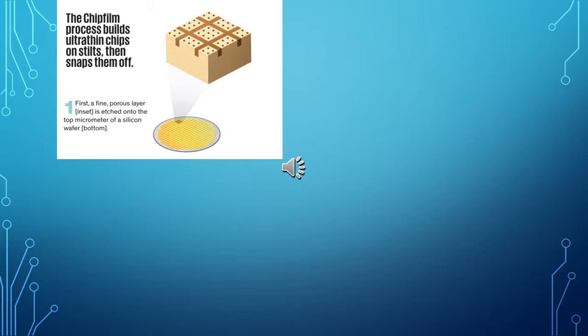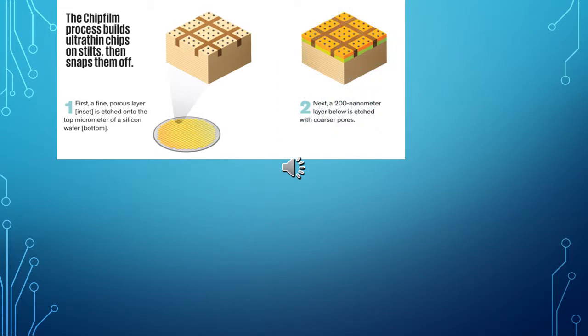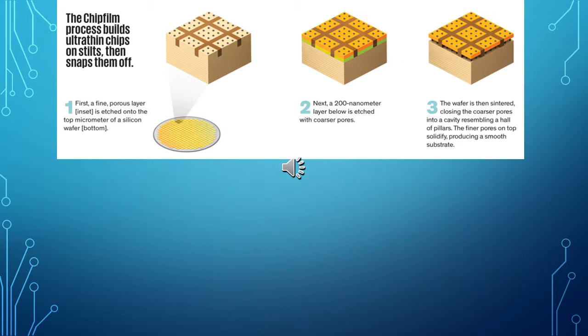First, a porous layer is etched onto the top micrometer of a silicon wafer. Next, below this top layer, a 200 nanometer layer is etched with coarser pores. This is followed by sintering of the wafer at high temperature, which means that the coarser pores close in into a cavity. It's kind of like a hall of pillars, with the pores being the pillars and the hall being the cavity. This produces a high quality smooth substrate.